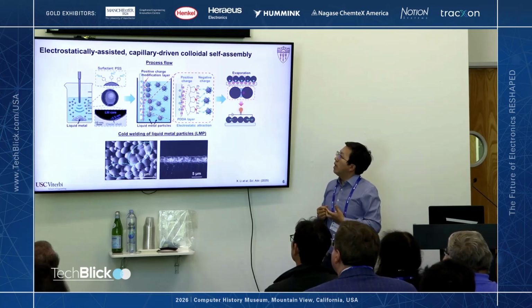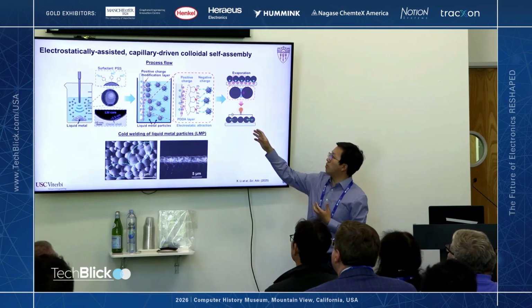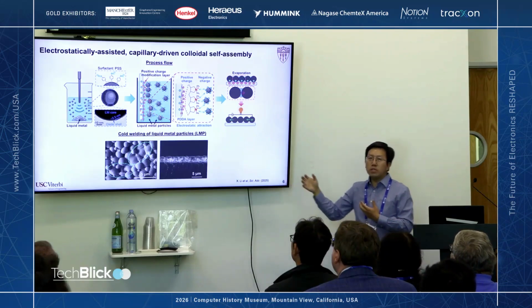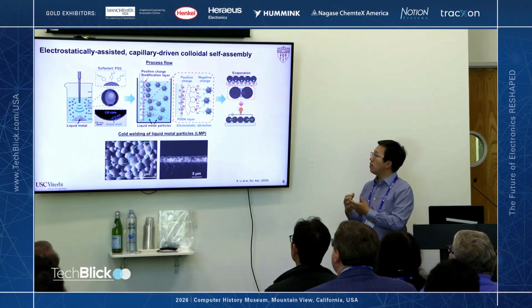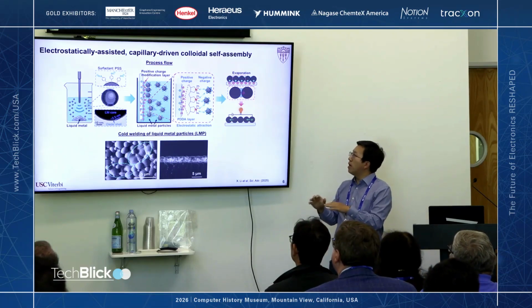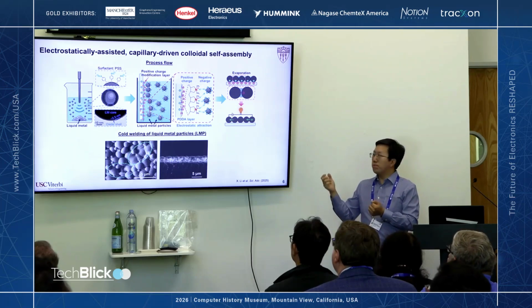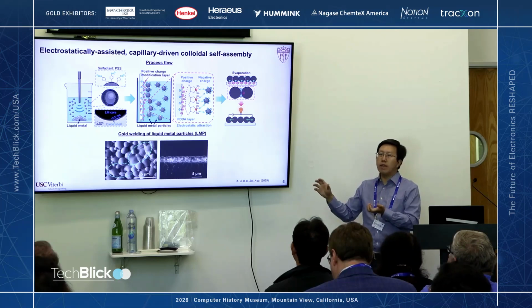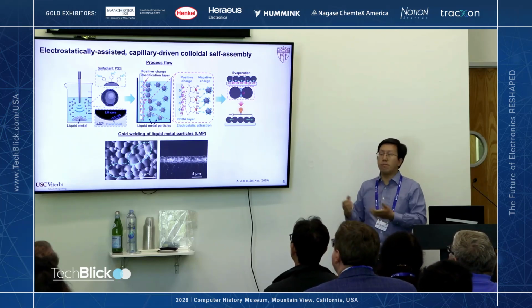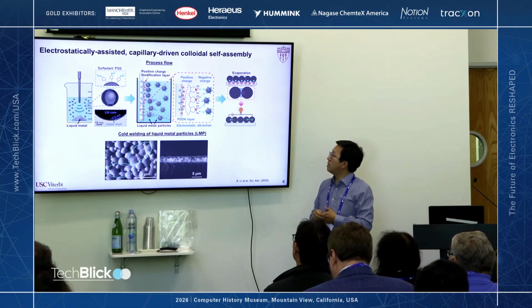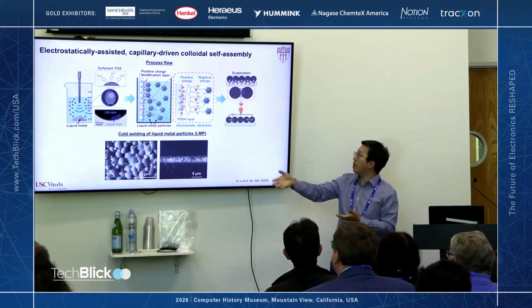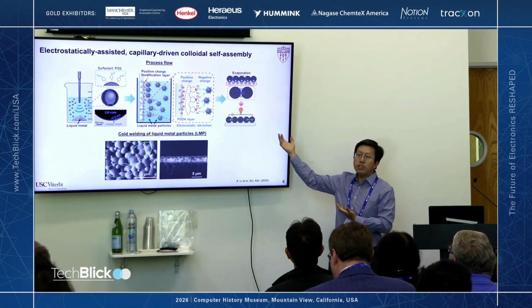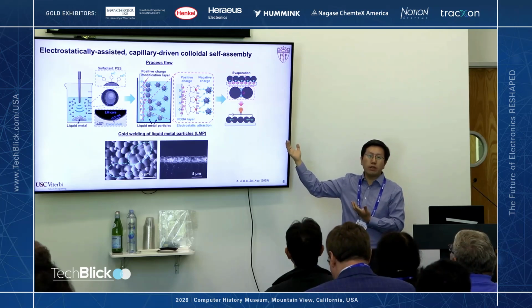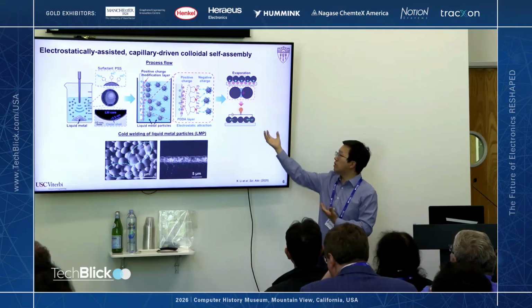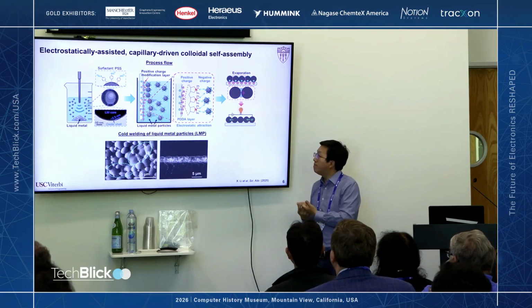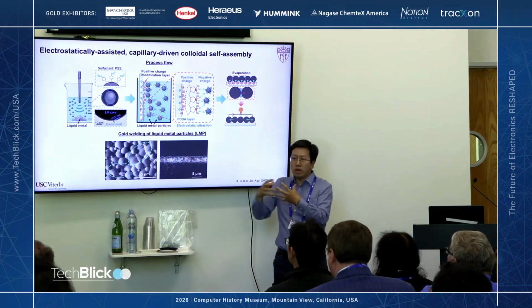What we did was we introduced electrostatic charge to the particles and to a receiving substrate. Because of the strong electrostatic attraction, the particles will be attracted to the solid substrate and form a thin layer. Because this process is self-limiting, you can basically form a single layer, and then you can repeat the process to get multiple layers. What's interesting about this process is that after you take this substrate out from the solution, there's solvent evaporation. That generates extremely large surface tension. That breaks the oxide skin, actually. So the particles are connected internally.